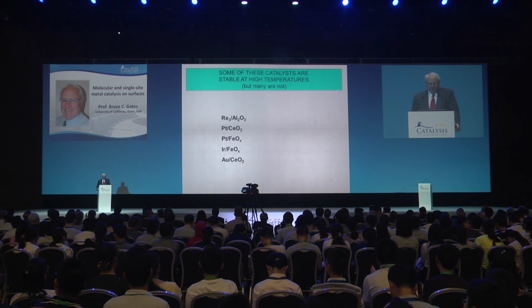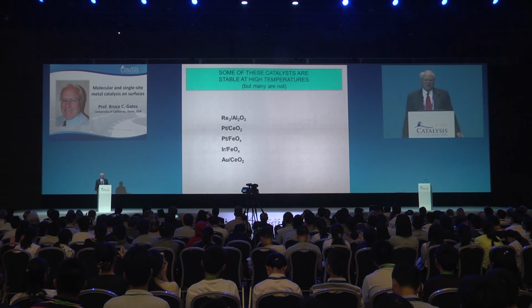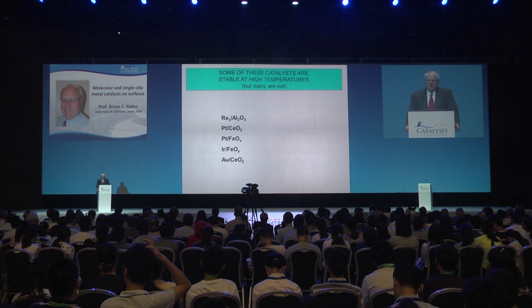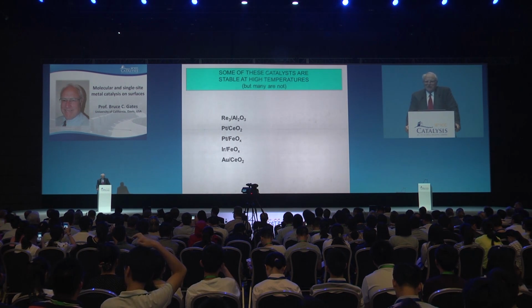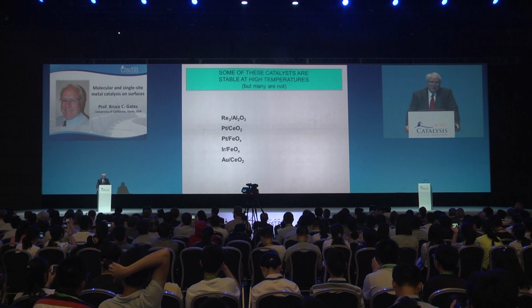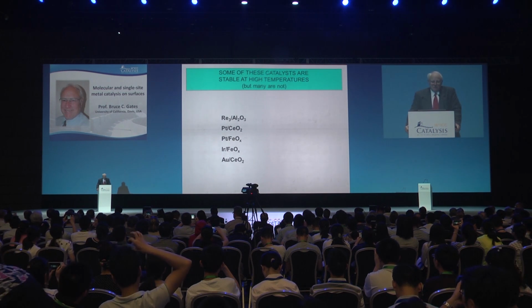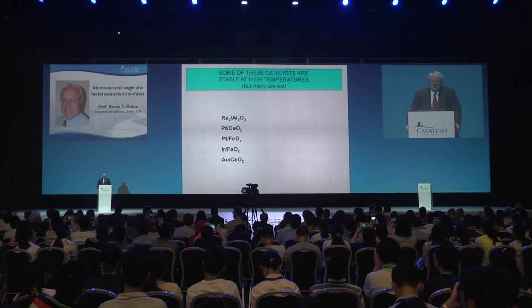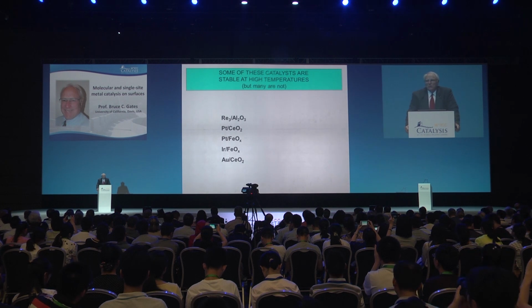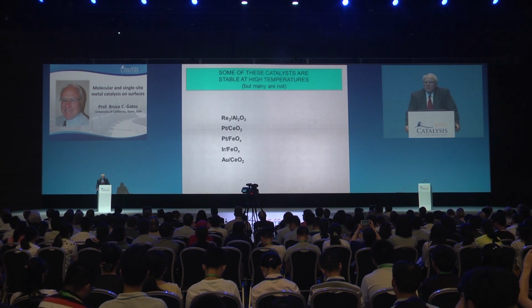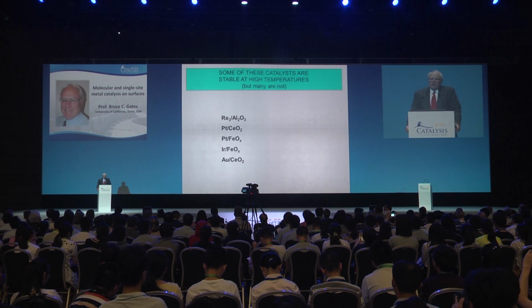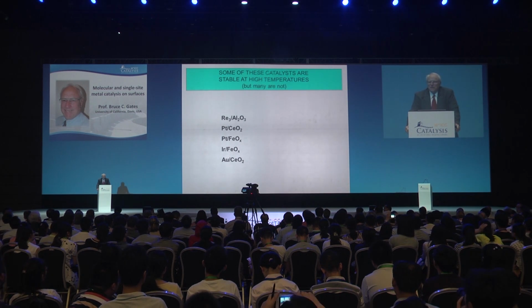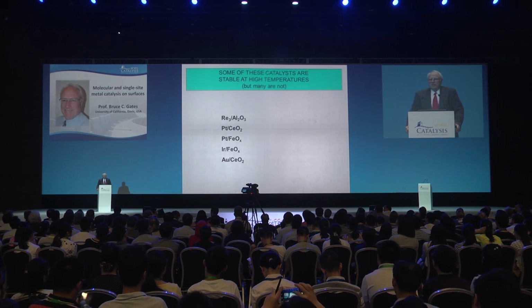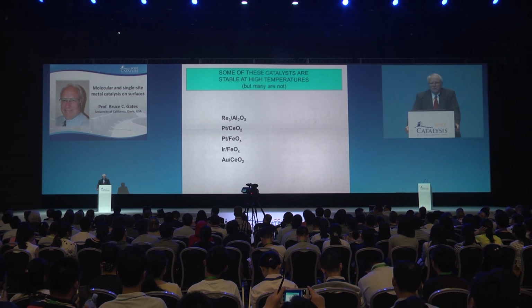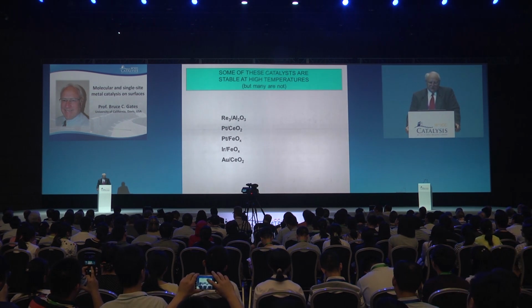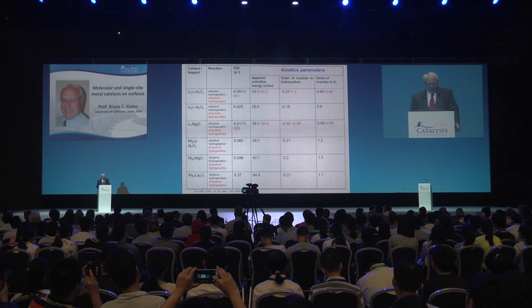A point I want to emphasize is that some such catalysts, incorporating not just oxophilic metals like group 7 rhenium, but more noble metals like platinum, iridium, and gold, are stable—a number of them—at quite forcing conditions, temperatures of 300 and 400 degrees C, for reactions of CO like CO oxidation and the water gas shift reaction. So this is a topic that's very timely and much in evidence at this meeting.